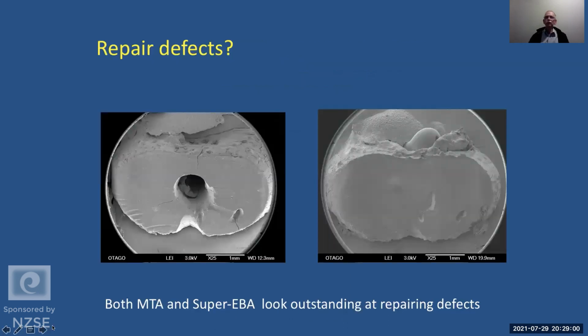We took it a little bit further down the track, and we looked at a tooth with a root end cavity in it with a defect in. This is where the ultrasonic tip has skated across the resected surface as an accident by the operator. And we sent that tooth away to be filled with mineral trioxide aggregate.